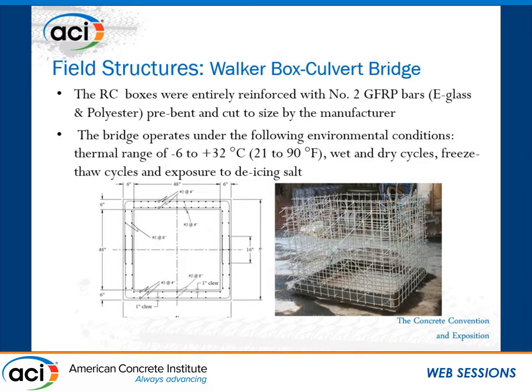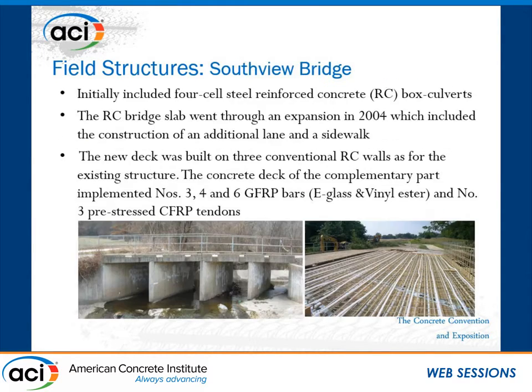In order to share with you the exposure of this bridge regarding the environmental situation, the bridge was exposed to a thermal range of -6 to +32 degrees centigrade, wet and dry cycles, freeze-thaw cycles, and also exposure to de-icing salts. So it has been exposed to different types of extreme situations, and it can provide us a good case study.